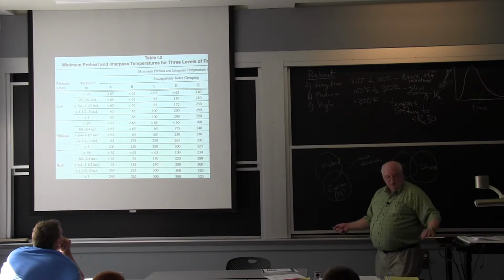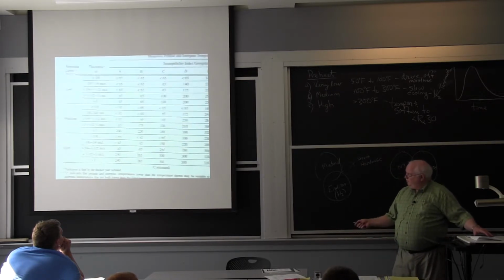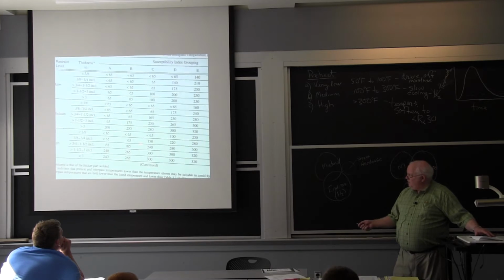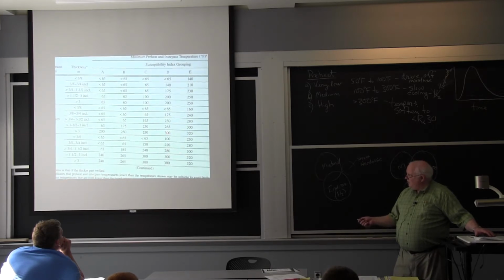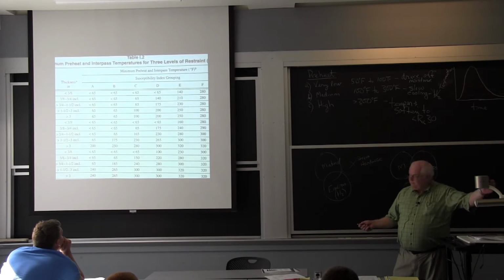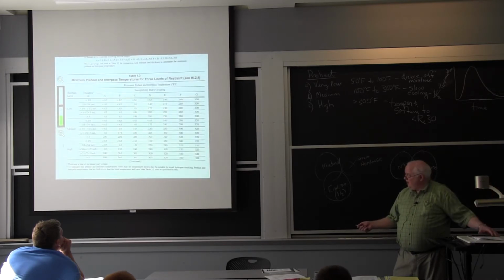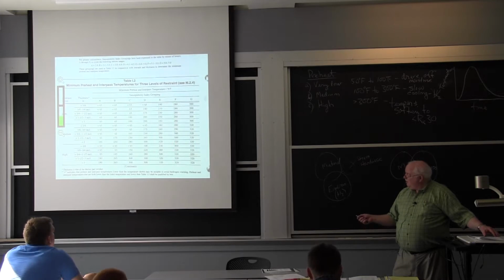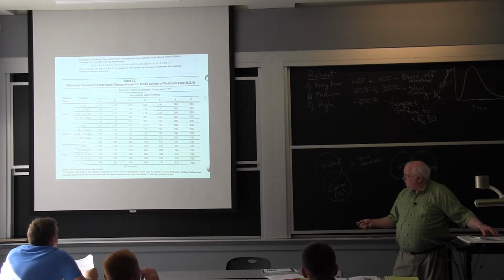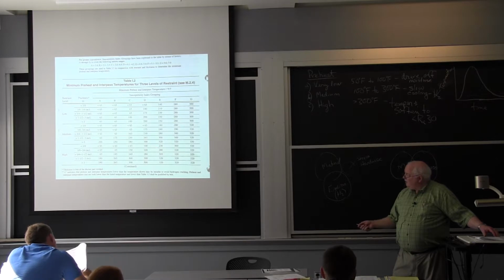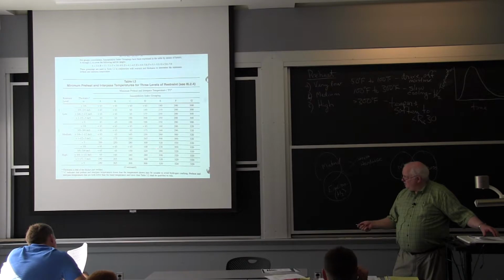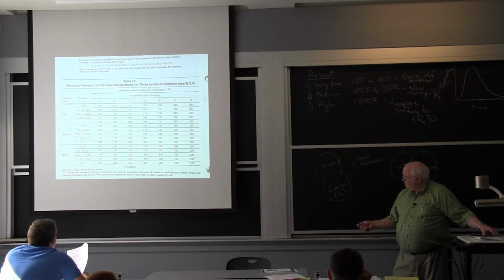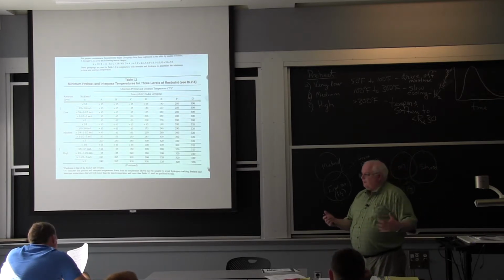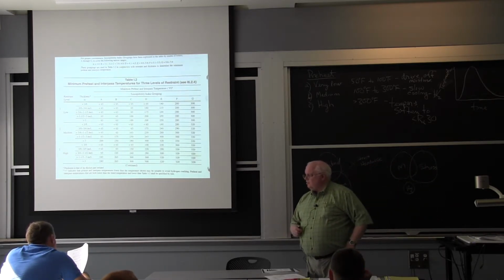And if you're now down into some bowels of the ship where these little sections have been cut up, and now I have to preheat these even higher because of the high restraint, I go from 250 to 320 in most cases, most thicknesses. And for the E, I'm still at kind of 280 to 320. Still, with high restraint, I still have to use a lot of preheat. Does that answer your question? It does. Thank you.